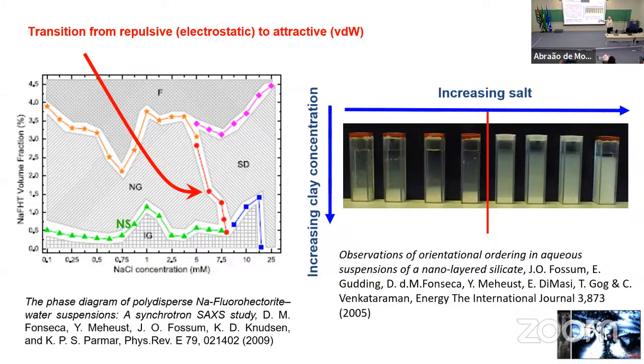So this is a system we have studied where we have measured the phase diagram, concentration and salt. And we can go from a repulsive nematic, where the distance between the platelets is governed by the size of the container and the concentration of the clay platelets, to an attractive nematic, where the distance is governed by the DLVO and a minimum decided by a combination of van der Waals attraction and electrostatic repulsion.